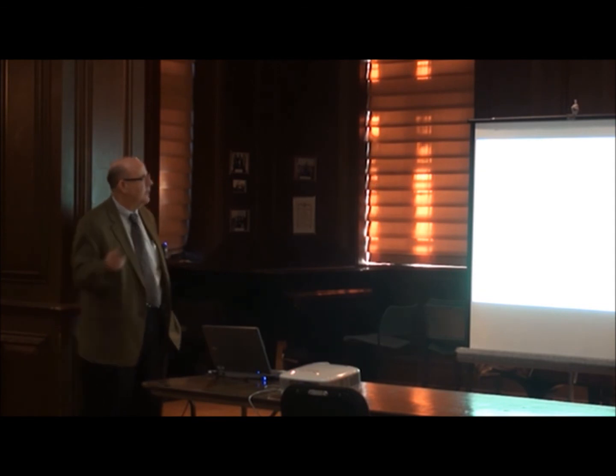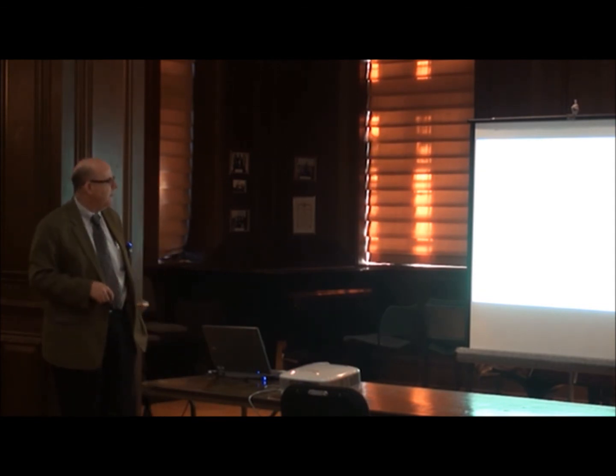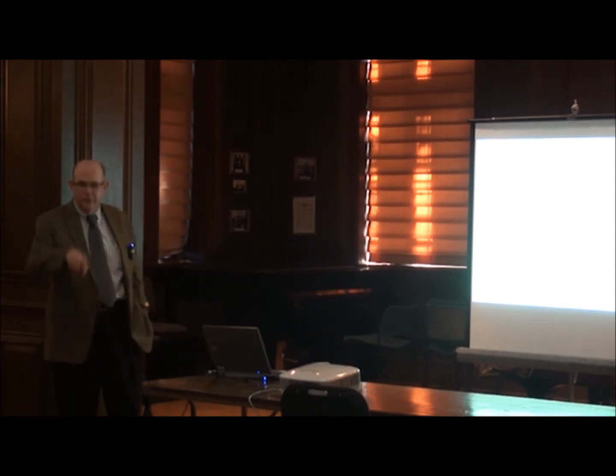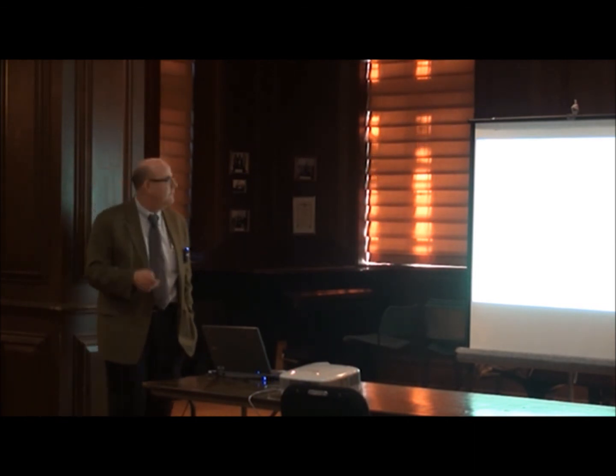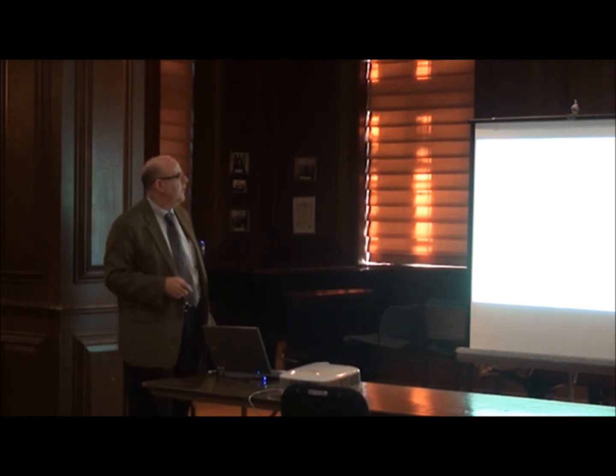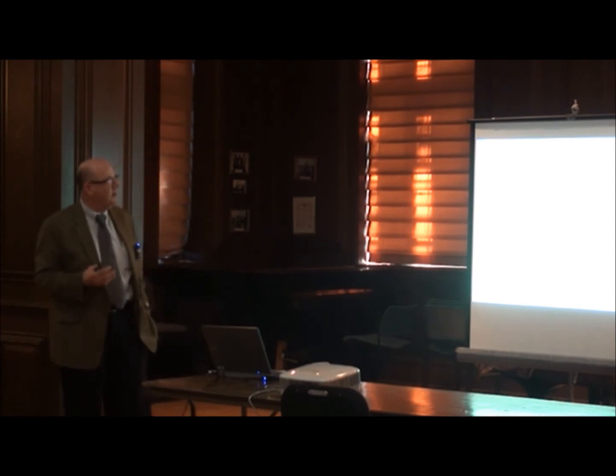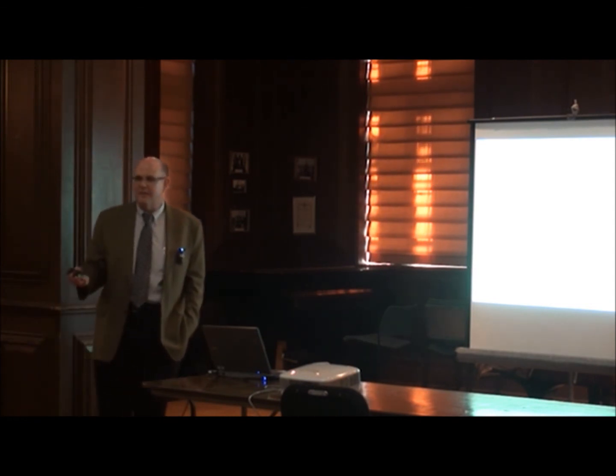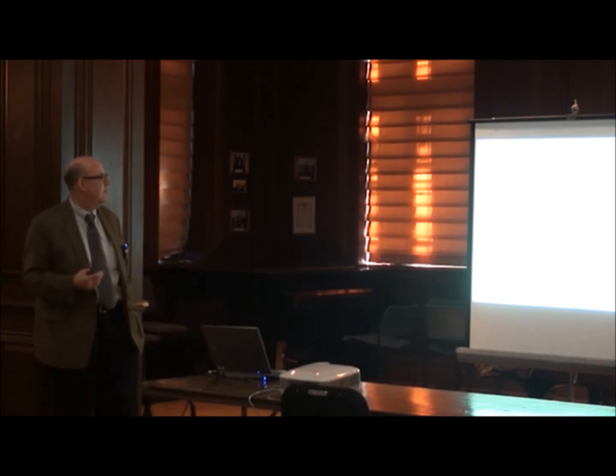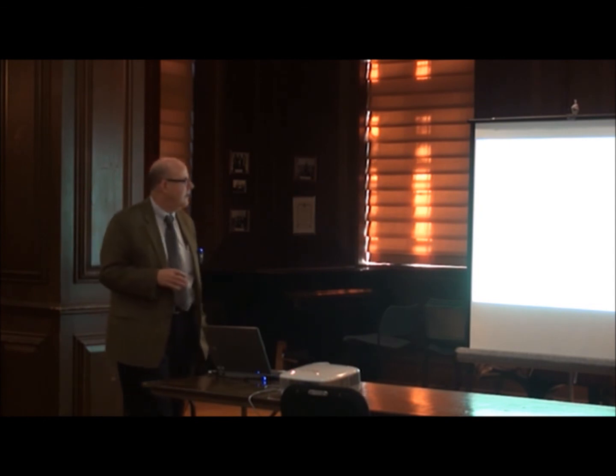And as a result of that, there's been a lot of papers where people are playing around with different kinds of surface textures, surface geometries, in order to affect fluid flow through the interface. So the final thought here is this: the understanding of the interface is really related to the flow and the factors that affect the flow. That's really what we're getting at with surface roughness. The film thickness and the viscosity relate to the ultimate friction. That's kind of where we're at.